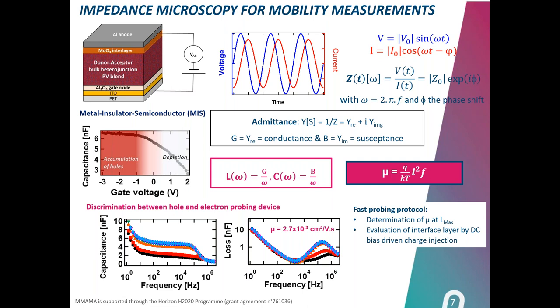The peculiarity of the protocol developed in MMAMA, based on some existing results in literature, was to incorporate gate oxide in the system to make the device much more capacitive. As you can see in the middle, the impedance measured could be converted into admittance, which is the opposite, from which two components could be extracted, either the conductance or the susceptance, and the susceptance is related to the loss. From the loss, the carrier mobility could be extracted.